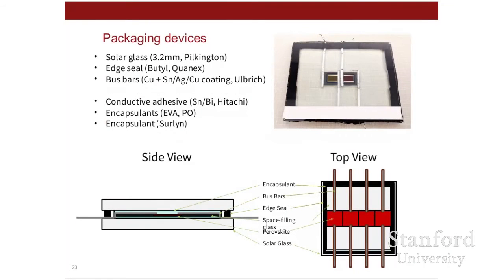And then the third really important strategy is simply to properly package these solar cells. And we talked a lot to the team at DuPont here in Silicon Valley who makes a lot of these packaging materials. And then we went to a company called D2 Solar that packages solar cells and makes panels for other solar cell startups that don't have all of that equipment. And here you put a rubber edge seal that you can see in black around the edge, and then in the interior you have encapsulation made of things like ethylene vinyl acetate or an ionomer called Surlyn, and then you pull vacuum to get any air out, and you heat it to about 130 degrees and press on it, and it forms a really nice package. And this is just industry standard packaging for solar cells.